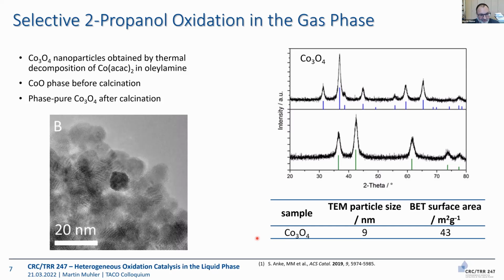The samples we get from our partners are a bit special. These samples originate from Stefan Schulz's group in Essen. He's using a molecular precursor, cobalt acetylacetonate, and that is decomposed thermally in a high boiling solvent. In this way, he generates cobalt monoxide nanoparticles, and when we calcine them, we have phase pure Co3O4. And that is a TEM image. You see many of these more or less spherical particles aggregated, and we can just take them as they are and fill them into the U-tube reactor.